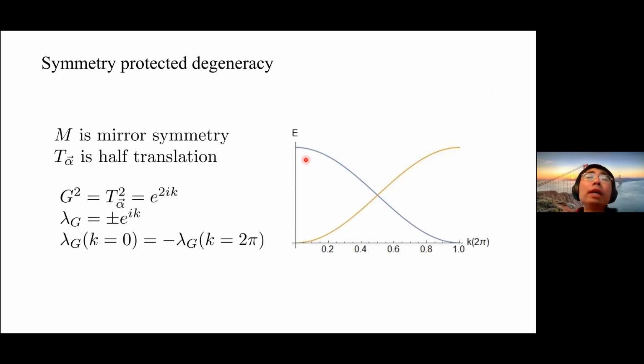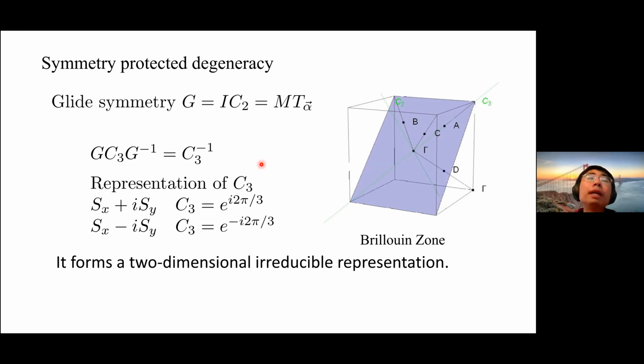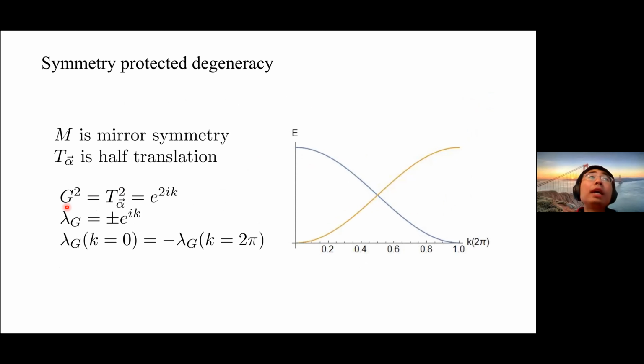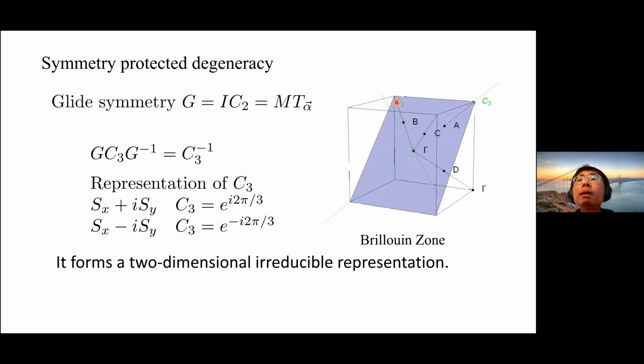On the other hand, if you look at gamma B, gamma C, and gamma D, these 3 lines lie in one of the glide planes. If they lie in one of the glide planes, you can compute their glide eigenvalue. What you can show is that this glide eigenvalue always changes sign once you increase the momentum along this direction by 2 pi, from plus sign to minus sign. In other words, the bands always show up in pairs inside the glide plane, so this is why we have a degeneracy somewhere on the glide plane - in this specific case on gamma B, gamma C, and gamma D, these high symmetry lines.